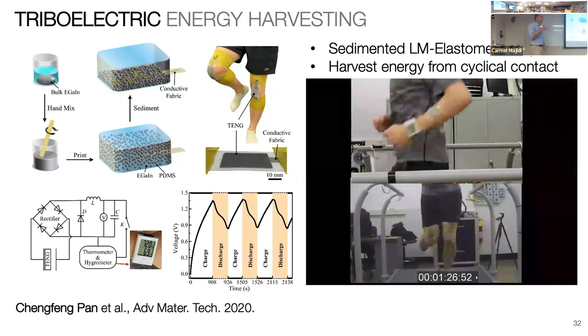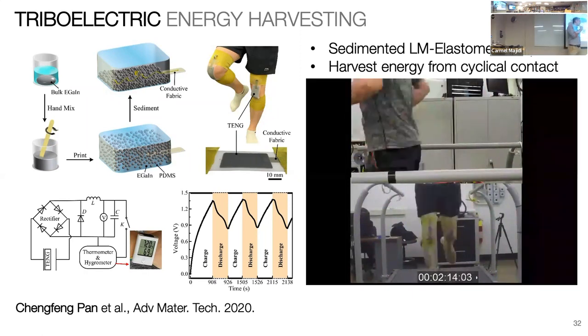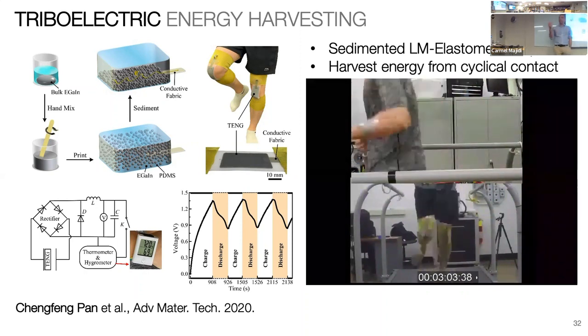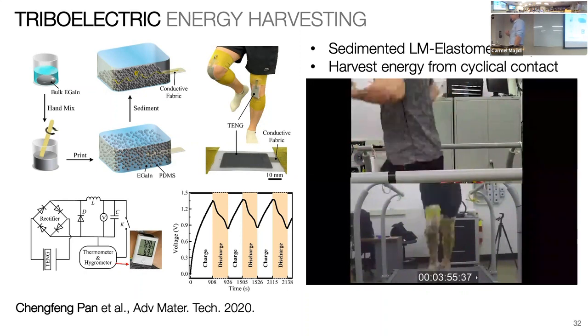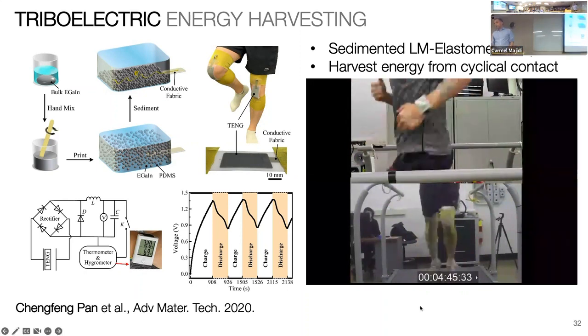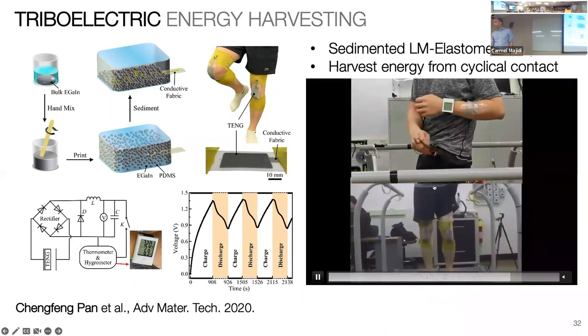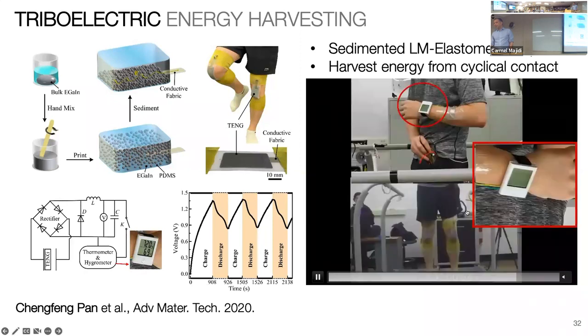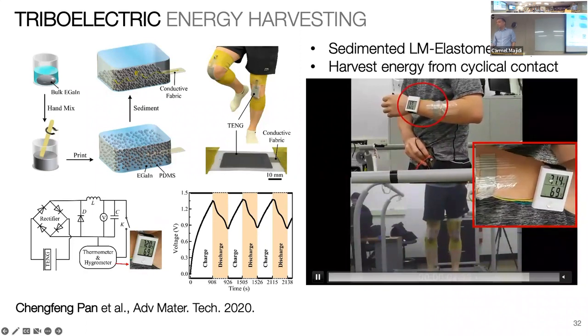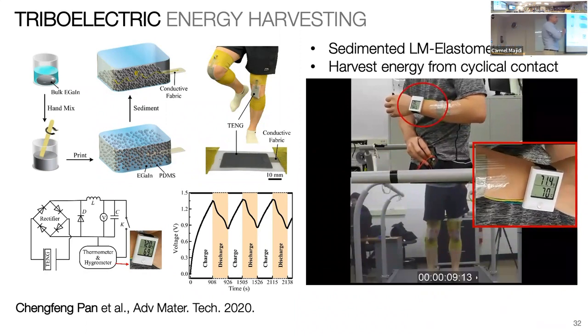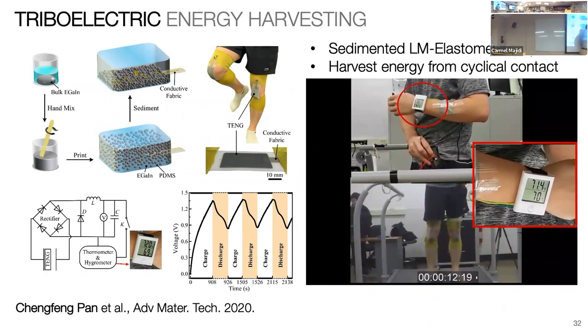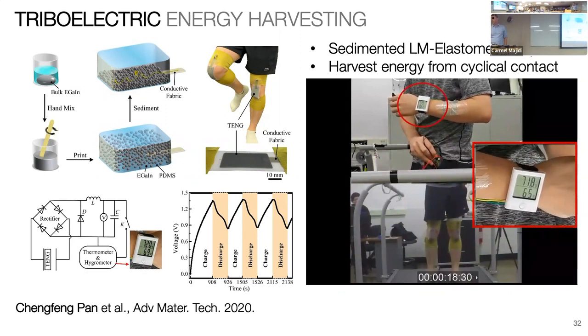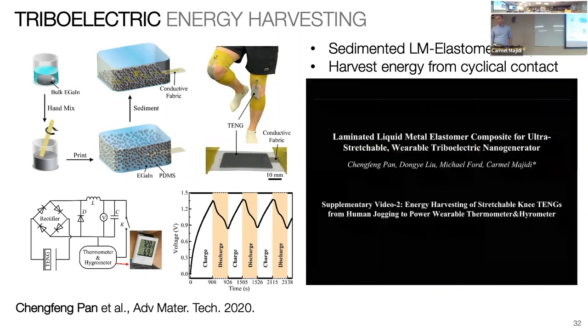Then, with subsequent contacts, you're varying the capacitance, and you can convert that into enhanced voltage that you can then harvest. In this case, we're harvesting that energy to power this body-mounted device. This is a very crude first pass at triboelectric energy harvesting with these devices. It takes about 15 minutes of jogging on a treadmill, but once you've primed it and created that charge, every 15 seconds or so you can recharge that device and collect data. So it's just another energy harvesting modality.